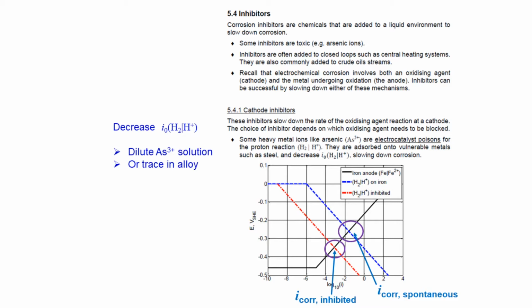The way arsenic ions work as an electrocatalyst poison is that they're actually relatively easily plated out of solution. It's analogous to the situation where I described for copper causing deposition corrosion when it ends up on aluminium, but the situation here is that some arsenic ions are plating out onto, say, the inside of a steel pipe, and then they simply poison the hydrogen evolution reaction, and therefore slow down the overall rate of the corrosion reaction that can take place. So unlike deposition corrosion, this addition of a corrosion inhibitor causes plating, which is actually very beneficial from a corrosion point of view because it slows down overall corrosion.